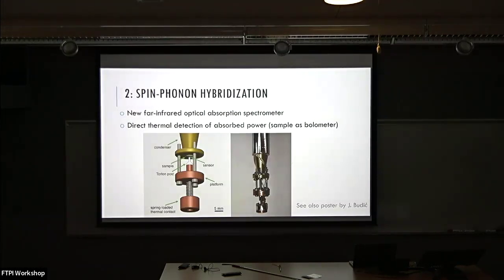Okay, this is what I mentioned. So basically, the thermal technique works, again, in a very simple way. You glue the sample to a thermometer, which is very sensitive. You modulate the light that falls on it, and you get some sort of modulated temperature signal, which you can measure with a lock-in. So this is all relatively easy to do. And the nice thing is that it's quasi-optics. So there's no transmission lines. It's just a light pipe, which is much bigger than the wavelength. And it essentially behaves like an optical spectrometer.